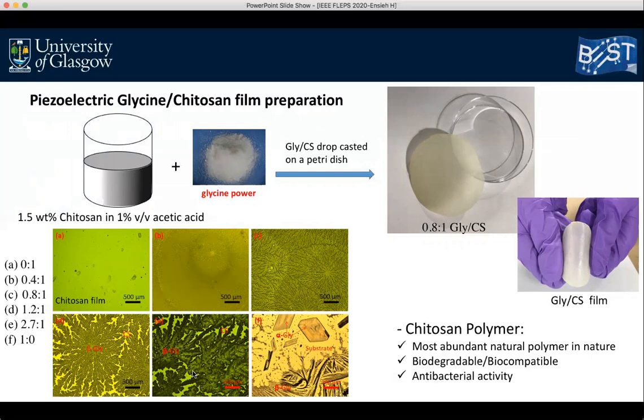And we observed with higher ratio of glycine to chitosan, just very thick and randomly oriented crystals. So this morphological change of glycine spherulite embedded in chitosan polymer with an increasing amount of glycine, in fact, shows us that the glycine grows with a different rate of crystallization. And then we just grew crystals from acetic solution without any chitosan polymer. We wanted to see the effect of chitosan on the polymorph selectivity of glycine molecules. And here we observe that mainly the bipyramidal crystal of alpha phase has been grown.